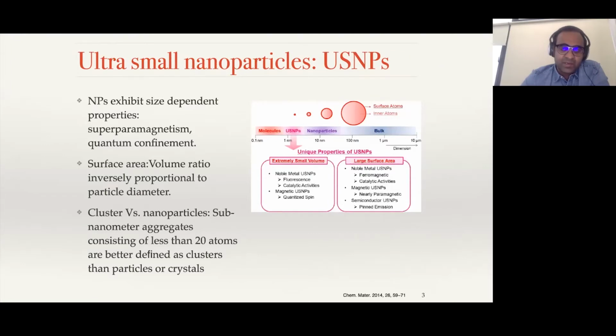So for example, if you talk about cadmium sulfide, cadmium selenide, or any of these chalcogenide nanomaterials or quantum dots, anywhere up to, let's say, 20, 30 nanometers, you would see that quantum confinement being very actively used. But when you go to 70, 80, 90, 100 nanometers, you actually are not exploiting that much. So would you still call it a nanomaterial? Now compare this with gold. If you reduce the size of gold from its bulk 1 micron size to, let's say, 100 nanometers, 80 nanometers, you'll start seeing that the gold is behaving in a very different manner.